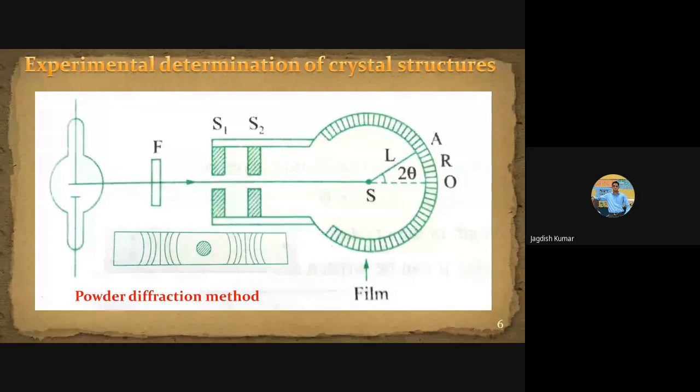So there, what we do is, we start with a model, and in our model we have a lattice, we choose a space group, and then we also choose the basis of atoms, where atoms are placed at specific positions, which we call the Wyckoff positions. Let me give you a quick overview of how we do Rietveld refinement. We take X-ray diffraction data, 2 theta versus intensity, and then in the software we choose some space group.